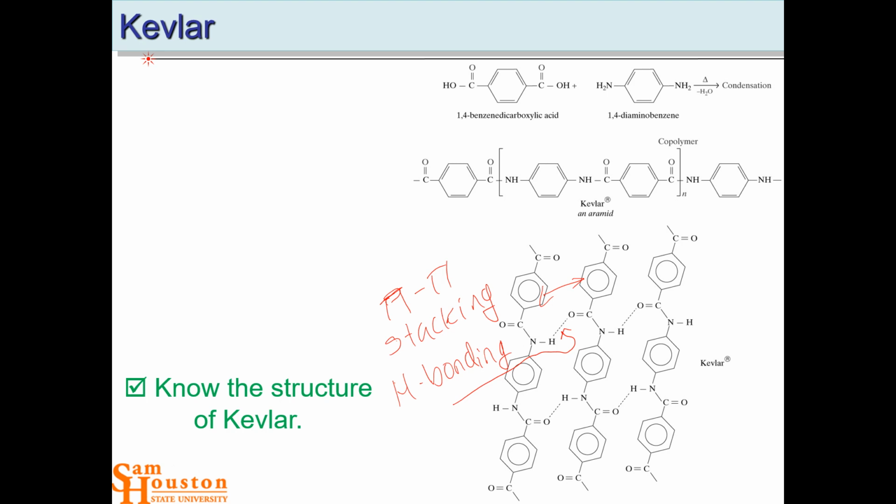So the kinetic energy of the bullet is being turned into the breaking of these hydrogen bonds and pi-pi interactions. And it stretches the fiber, but we're burning up all those energy units by breaking those non-covalent associations and protecting the covalent associations. Now, some of those covalent bonds do break, but fewer break in Kevlar than would break in, say, polyethylene. So that's one of the wonderful things about this particular polymer, and that's why it makes such strong fibers.